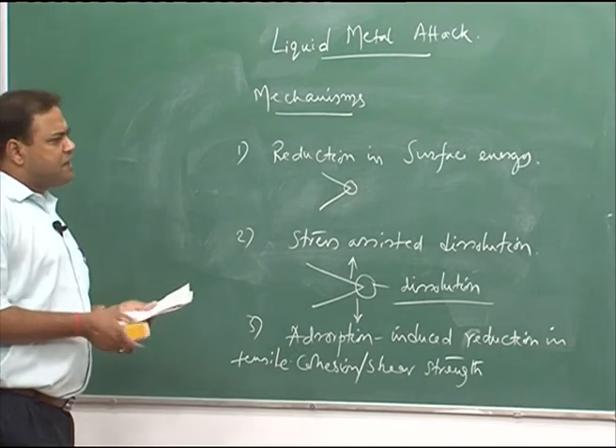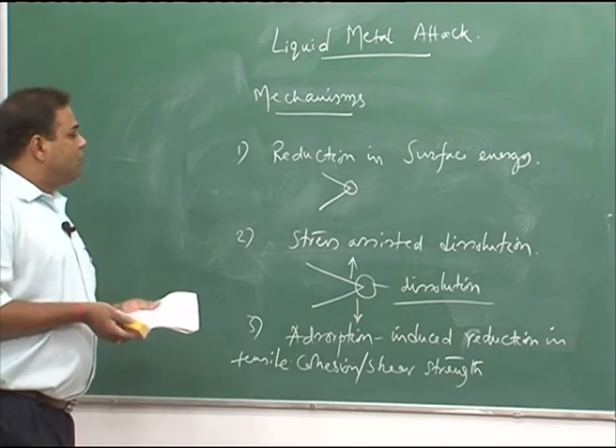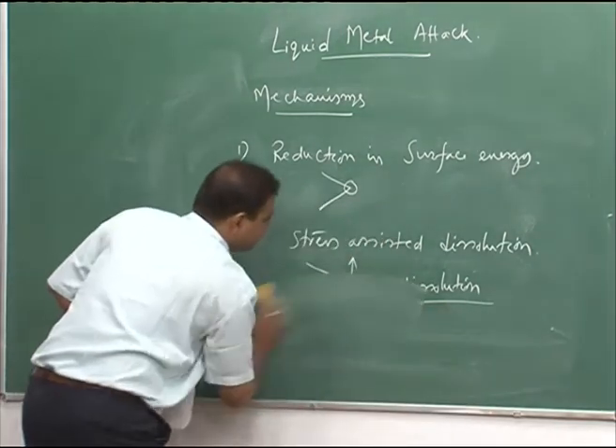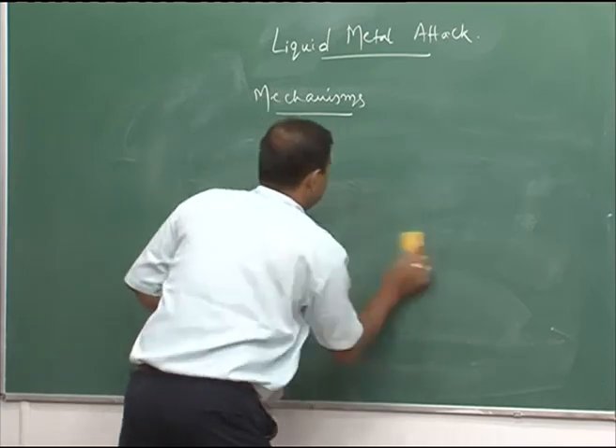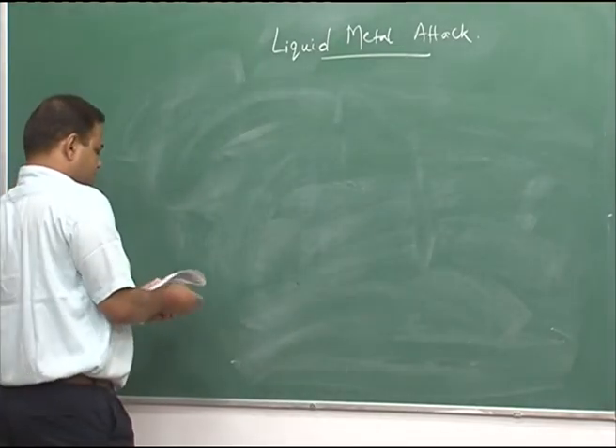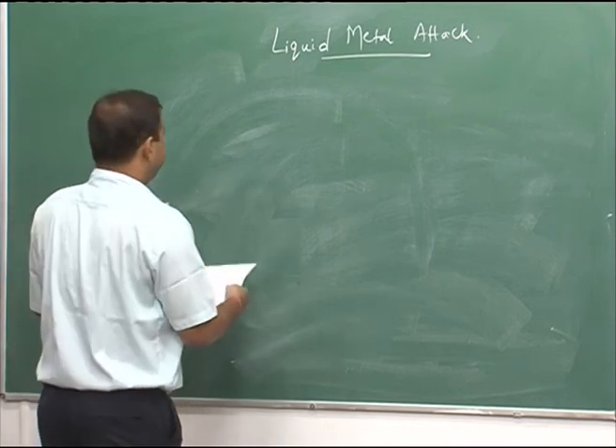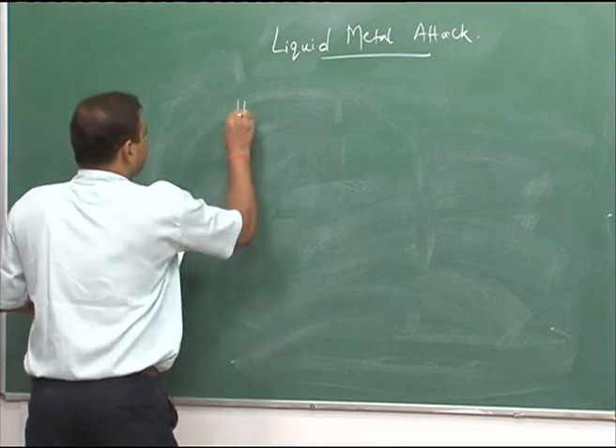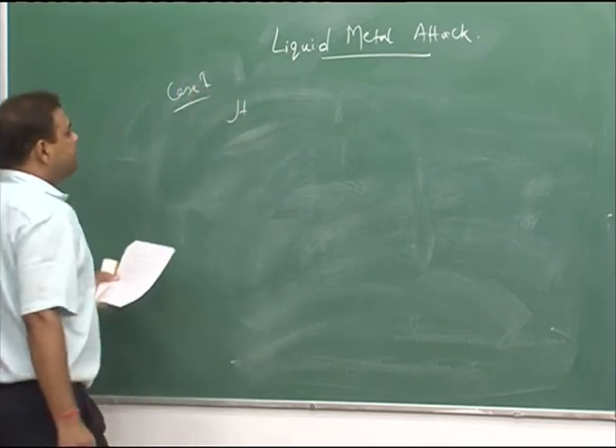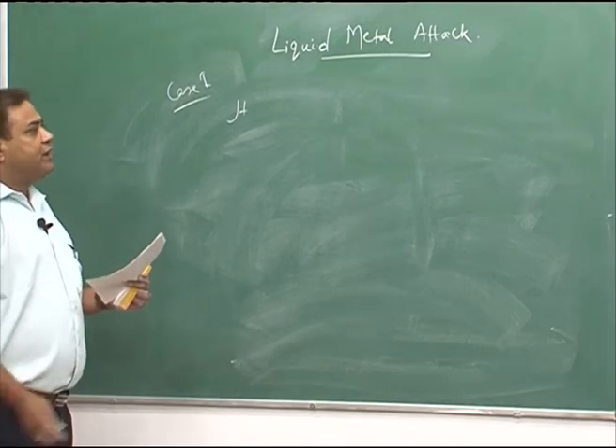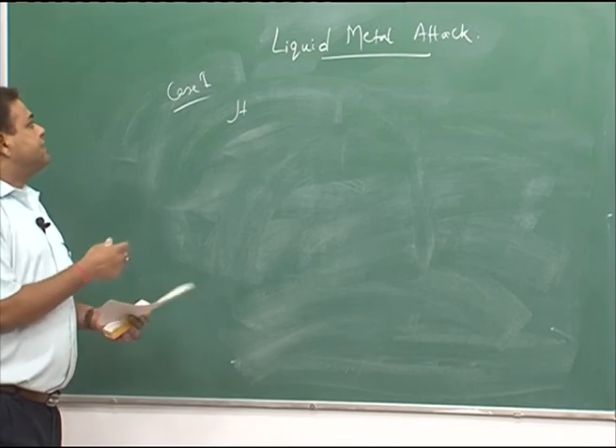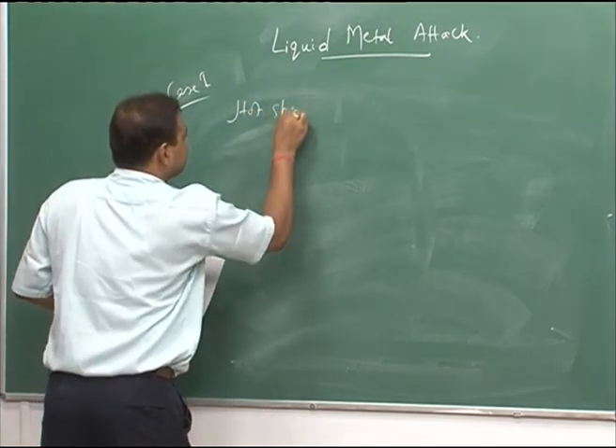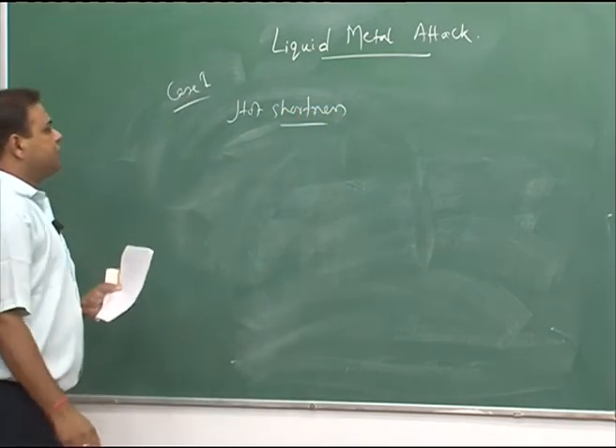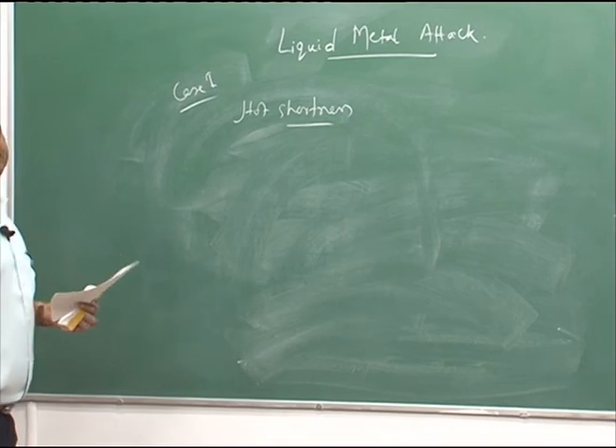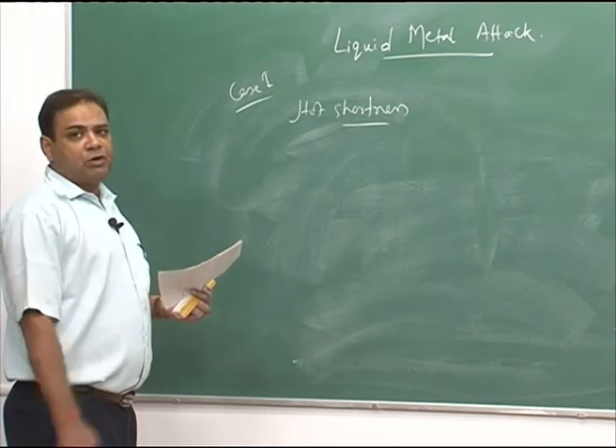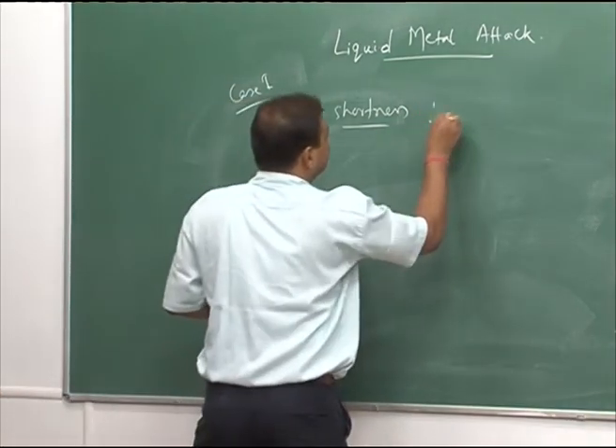Now, there are many examples of this liquid metal embrittlement effect. A few examples, the case studies, let me put forward. One is case 1, sometimes in case of copper containing steel, when that steel is hot rolled, we sometimes experience hot shortness. Hot shortness in case of steel is related to low melting compound formation along the grain boundary. So, in this case, if we have a high copper